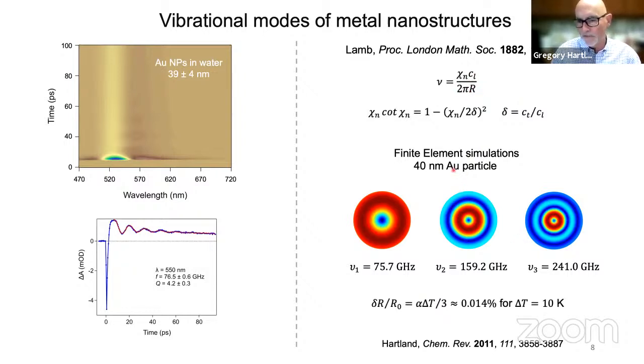So for a finite element simulation of a 40 nanometer particle, you predict a frequency of about 76 gigahertz, right? So it basically matches what you expect from continuum mechanics exactly. There's also an analytic expression that comes from this wonderful paper by Horace Lamb in 1882, well over 100 years ago, where he worked out an eigenvalue equation for the frequency of the breathing mode.